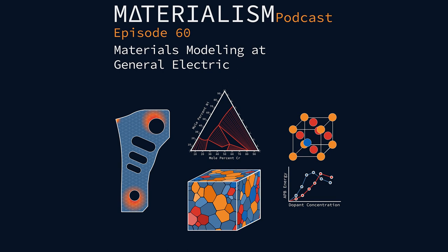The other great thing is that the material's matrix phase has a low stacking fault energy, which enhances the creep strength. Essentially, in the FCC matrix, it's energetically favorable for dislocations to split into partials. If they encounter a precipitate that they cannot shear because of the previously discussed high energy anti-phase boundaries, they could try to recombine via a cross-slip mechanism, which is where they shift what slip plane they're moving along. But stacking fault energy in the matrix is really what determines whether or not this cross-slip is going to occur. And because it's so low in the matrix, it becomes unlikely. And so you end up having the splitting of partials, which means they can't recombine and continue to move elsewhere. And that allows you to resist creep.